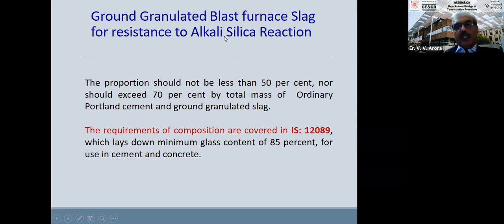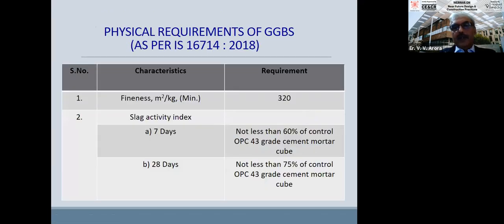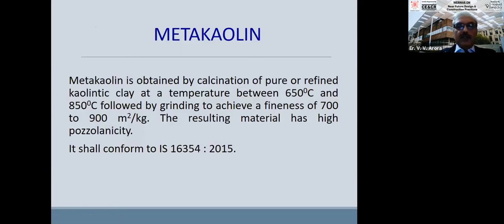This is also very good for resistance to alkali silica reaction. Wherever the aggregates are prone to alkali silica reaction, GGBS is used, and in that case a minimum of 50% has to be used to be effective against the alkali silica reaction. The requirements are covered in IS 12089. These are the physical requirements of GGBS.